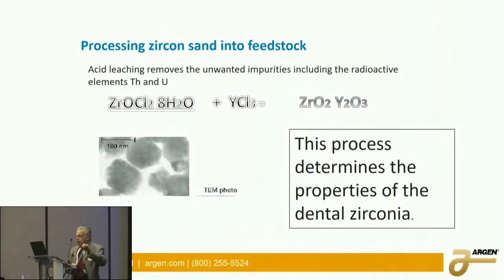Now, originally, they added a material called magnesia, which of course is magnesium with oxygen. And that material stabilized the tetragonal form of the zirconia, and that's the high strength form that can be used for processing materials. And that was called a ceramic steel. And unfortunately, some of our friends in the dental industry have used that in the case of yttria stabilized material, but it's not the same material. Now, I mention that because the yttria combination actually makes it stronger than the magnesia combination. So we're dealing with a material that's much stronger than what was developed back in the 80s.